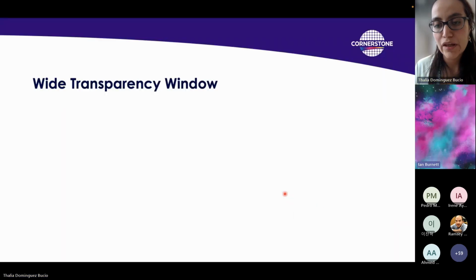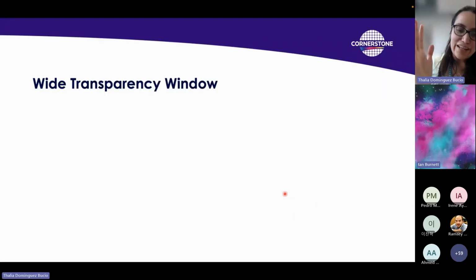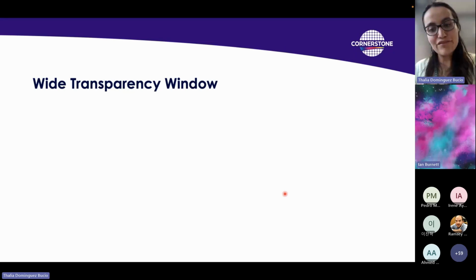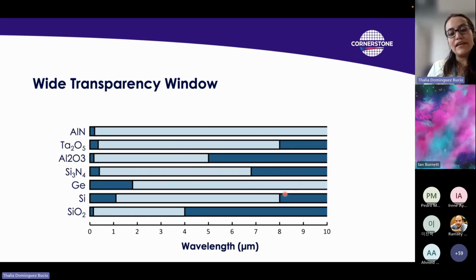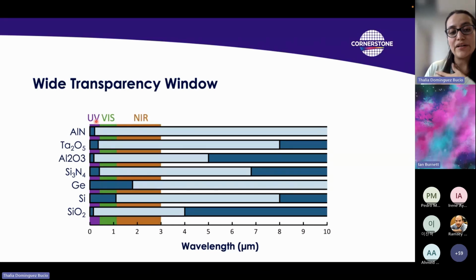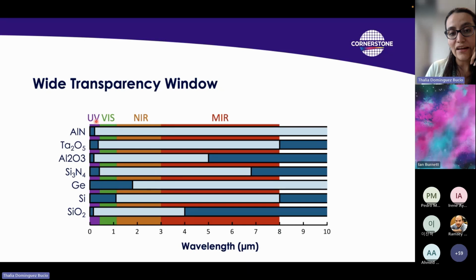Now, as I mentioned, we can tune the composition of our silicon nitride layers all the way from nitrogen-rich to silicon-rich, and that will change the band gap of the material. And this band gap is related to the transparency window of the material. So if we look at the transparency window of typical integrated photonics materials, we will see that there are some materials that are transparent in the UV part of the spectrum. Some of them are transparent in the visible part of the spectrum, some of them in the near infrared, and some of them in mid-infrared.